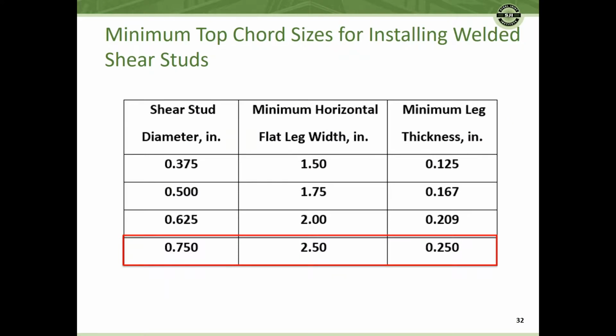Now, as you can see, this table defines suggested minimum horizontal top chord leg length and leg thicknesses. And why do we need a minimum horizontal leg for installing studs? Because leg lengths less than those shown in the table make installation of welded shear studs difficult. And also, in the table, minimum top chord thickness is required. So for each stud diameter, like if you look at 3/4 inch stud diameter, a minimum leg thickness of a quarter. And this is to keep the stud diameter to top chord thickness ratio less than or equal to 3. 3 is the highest SJI permitted value for this ratio. AISC allows a different limit, and we'll talk about that.